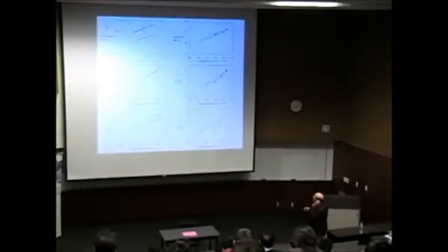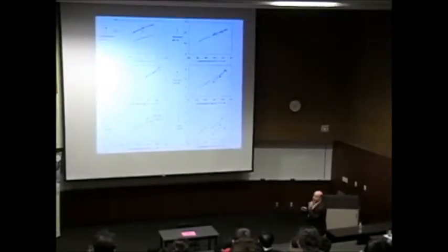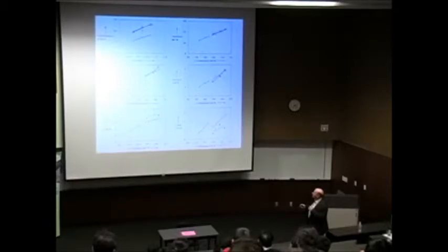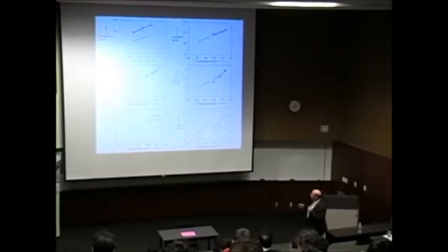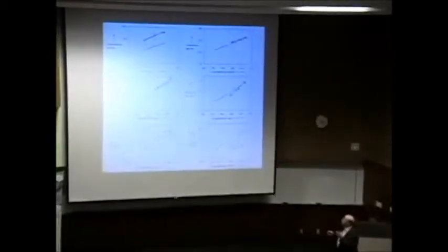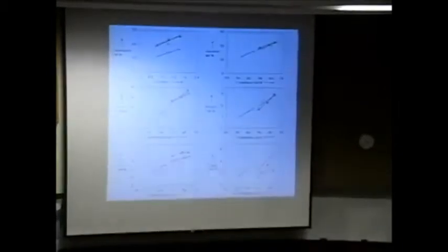What is really different and exciting is that the amount of diesel fuel that you make can be substantially better with a mesoporous form of the zeolite than a non-mesoporous form. So if I extrapolate this out to the same conversion up here, let's say, it may intersect the red line, but it certainly is lower than the green line, which is a more mesoporous form of the zeolite.